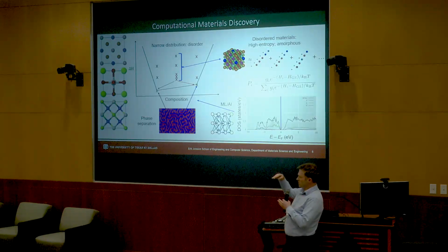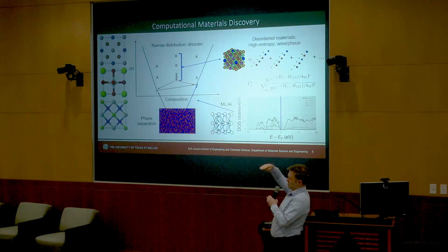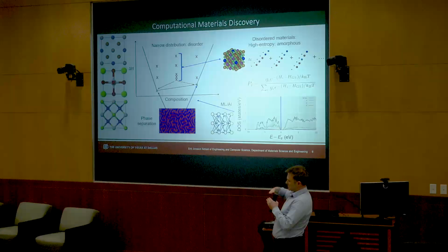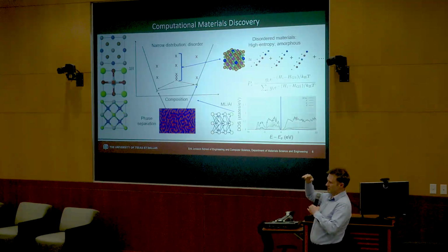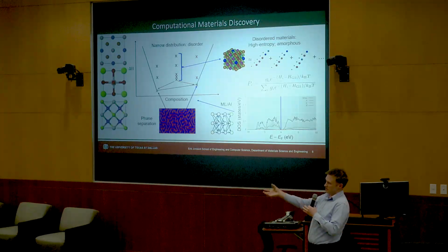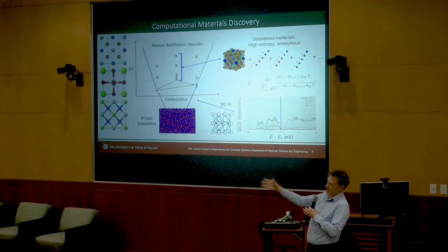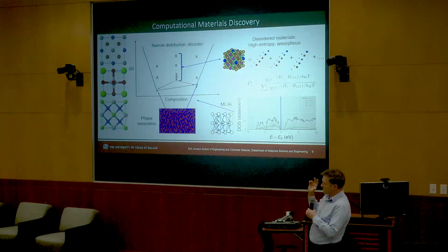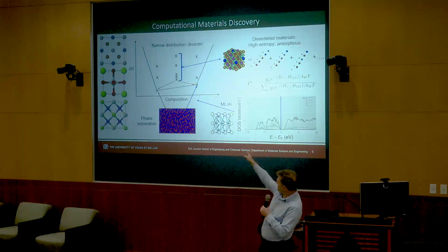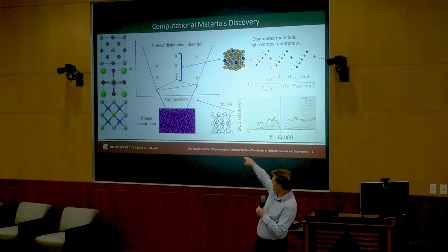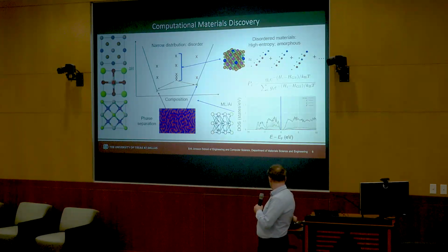And then we can look at the energy differences between the pure elemental components that make it up and the actual materials that we've calculated. This is what we call the formation enthalpy. This is the amount of energy you get out when, for example, you take magnesium and oxygen and make magnesium oxide. This tells us something about the stability of this material, how easy it's going to be to synthesize. And we plot this, you see this graph in the middle with delta H versus composition.